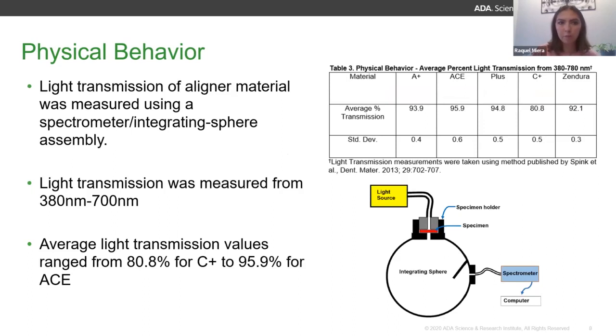For our physical behavior, we measured the light transmission of aligner material using a spectrometer and an integrating sphere assembly. We measured the light transmission from 380 nanometers to 700 nanometers, and our average values ranged from 80.8% light transmittance to 95.9%.